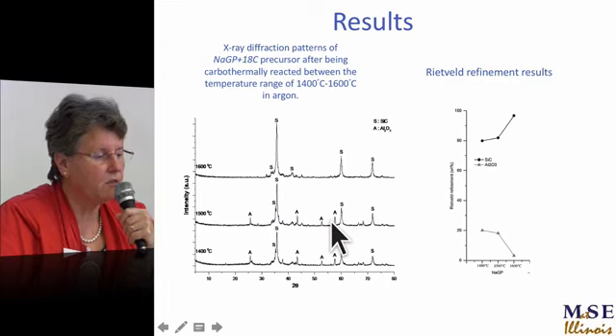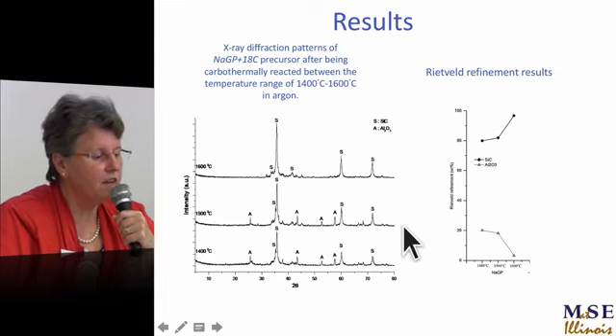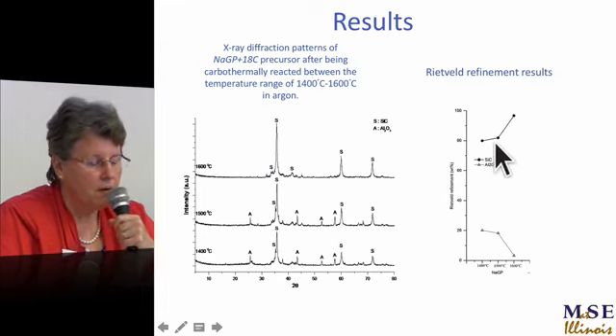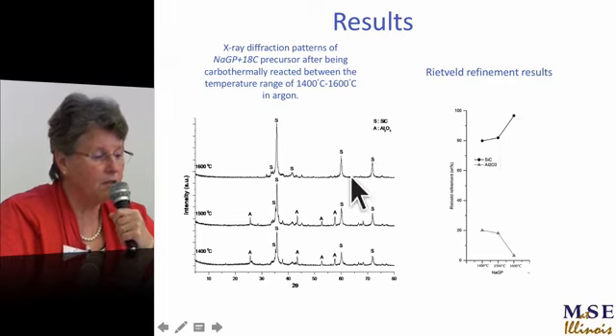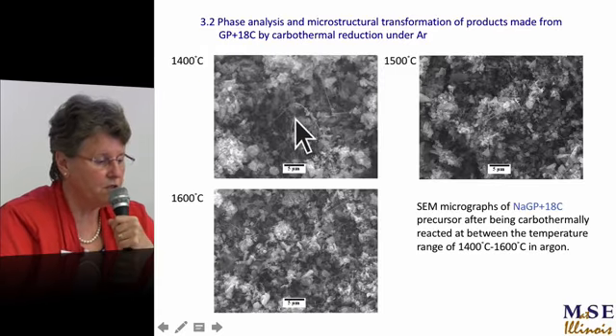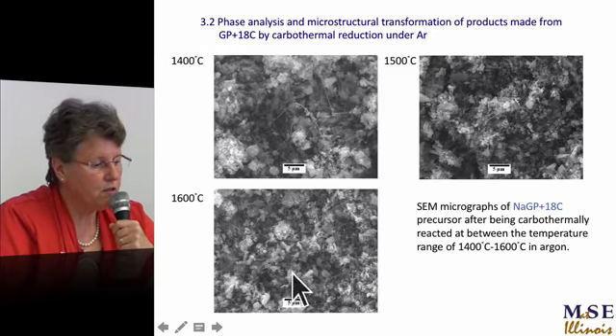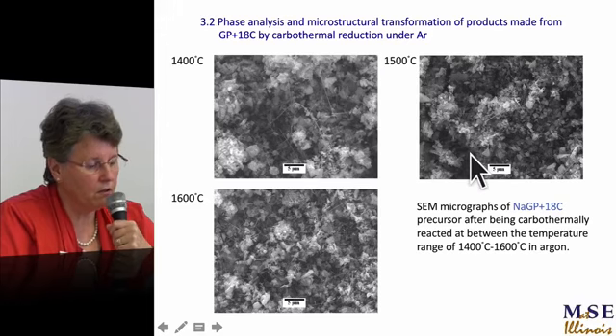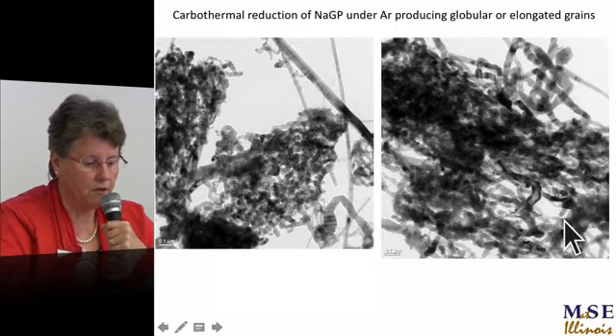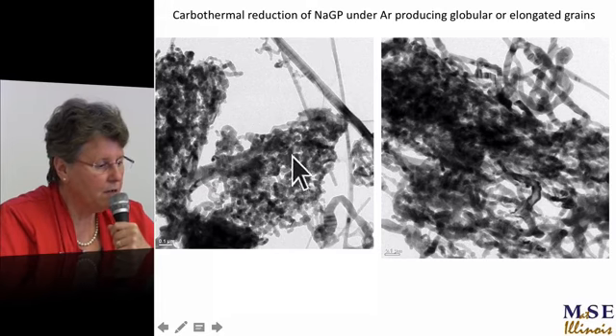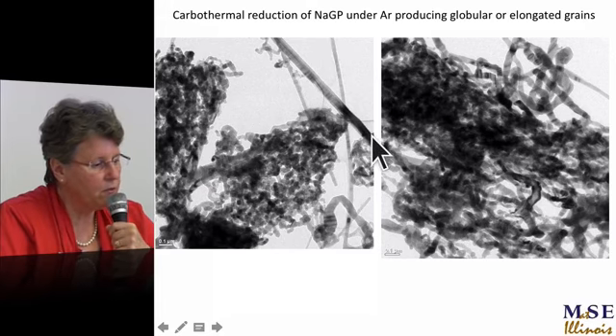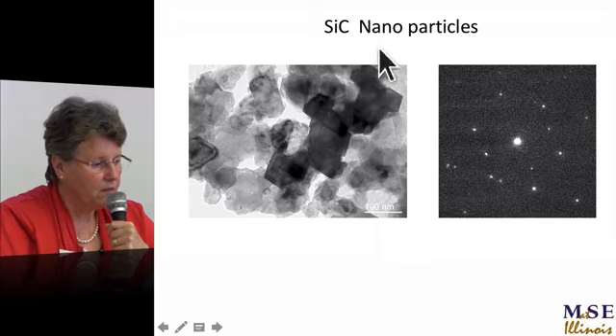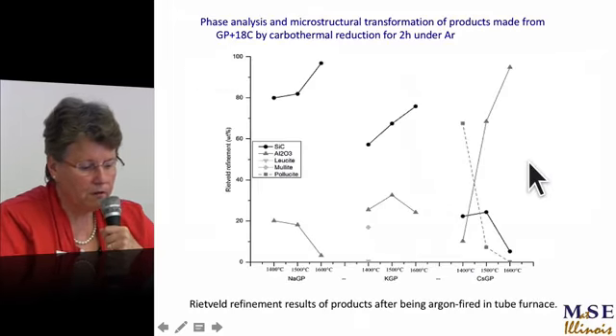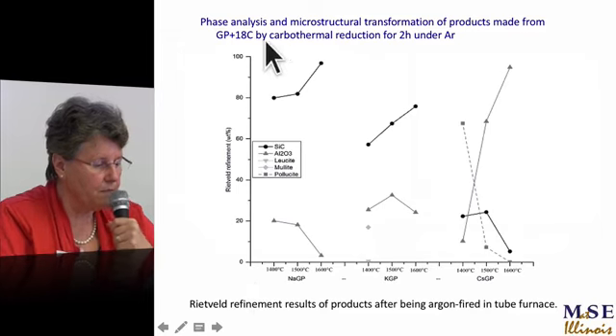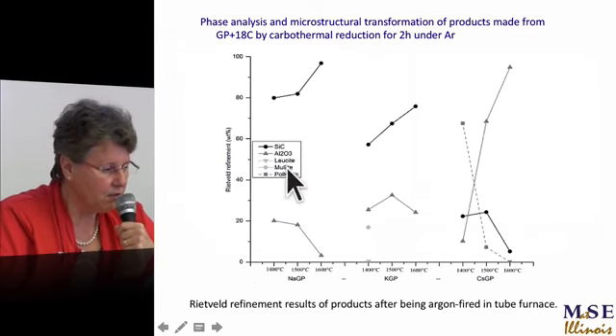Now, if you were to make alumina silicon carbide composites, you'd take this and hot press it. But here you can make just about pure silicon carbide at this low temperature. And the SEM shows that it's nano soft agglomerates, that's sodium. In the TEM, it looks like nanoparticles and sometimes needles, whiskers. Silicon carbide nanoparticles.